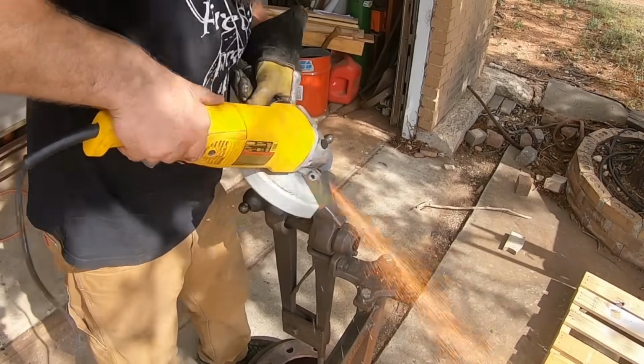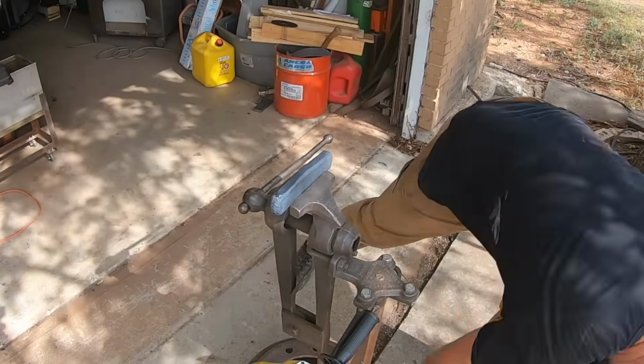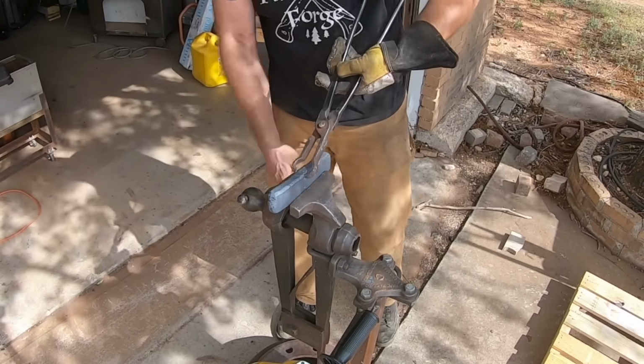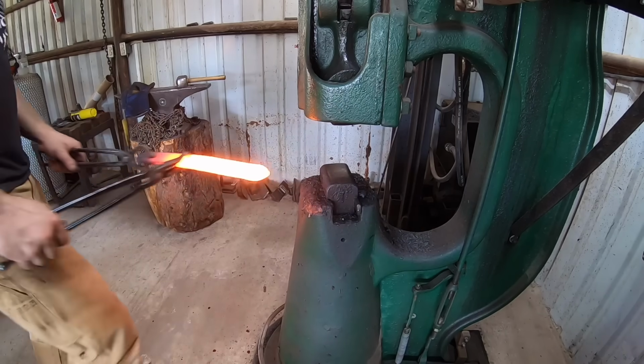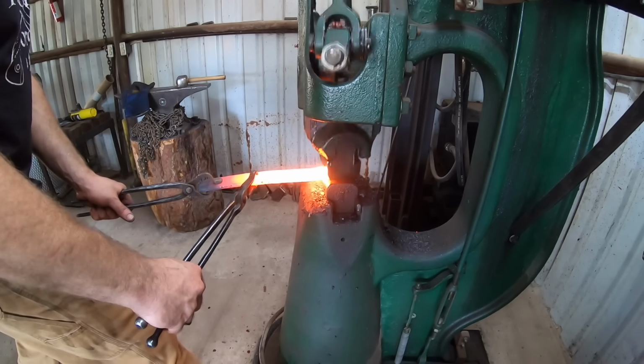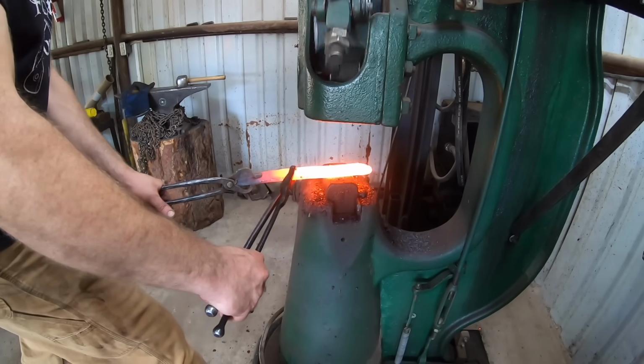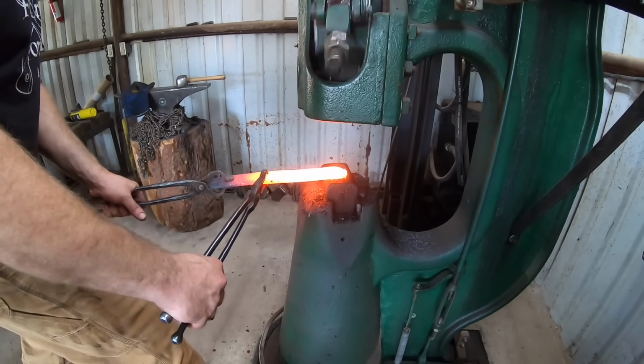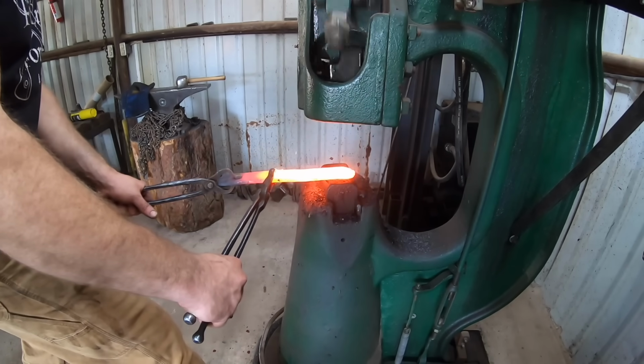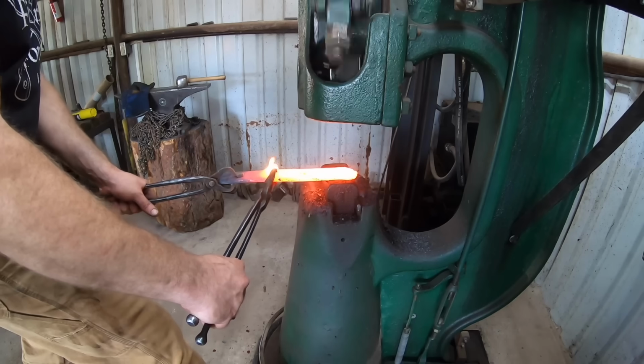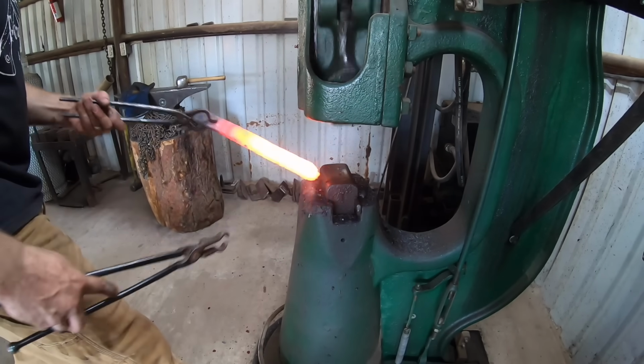Had to go back and forth a couple of times and grind out inclusions or cracks on the edges of the billet. This is pretty par for the course on ball bearing Canister Damascus. The reason for that is because as you compress that in the V-shaped dies, you're actually stretching the billet as well as compressing it widthwise.